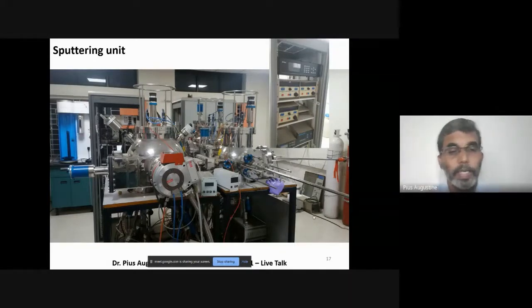So both in sputtering as well as in PLD, we can load many targets, maybe 3 targets. In PLD we can go even up to 5 targets. And in PLD we can control the number of laser shots. It is the number of laser shots which decides the thickness of the film developed. So by optimizing the number of shots and energy, etc., we can get even a 1 atomic layer thick thin film. Similarly, suppose you want to deposit 1 or 2 atomic layers of one particular film, and immediately after that you want to deposit another atomic layer or another thin film, nano layer, then another layer, like that you can go for a multi-layer film.